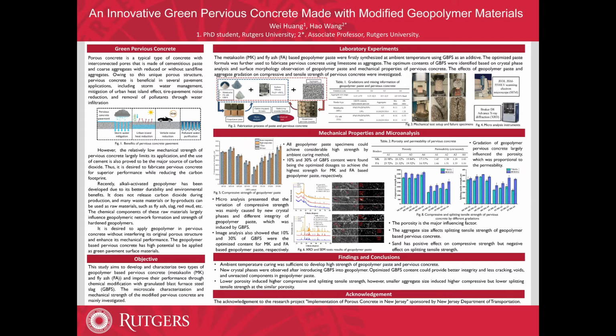We also did the compressive and the splitting tensile test for the geopolymer pervious concrete. Results are shown in Figure 8. We can find here, the porosity is a major influencing factor. With the reduction of the porosity, the compressive strength and the splitting tensile strength will increase.